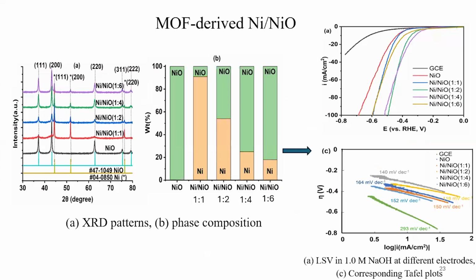For the other composite, the nickel and nickel oxide composite, we found that the use of different molar ratios of nickel salt and organic ligand will give different kinds of materials and of course different properties of hydrogen evolution. For example, on this slide, we can see that different amounts of organic ligand will form different nickel and nickel oxide with different nickel to nickel oxide molar ratios. And this, of course, affects the performance. In this study, the material with the molar ratio of 1:2 gives the best results.